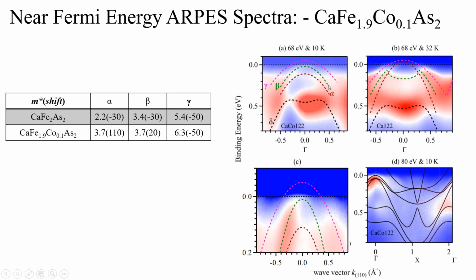cobalt doped compounds. So basically what I want to say is, with the cobalt doping, what do we expect? We expect that the Fermi energy will shift, the whole bands will go down. However, in this case, we see that the bands are not going down. Some of them are going down, but most of them are not. So it means that replacing iron with cobalt is not just leading to charge carrier doping. It is also creating a significant amount of correlation in the compound, which is not well captured in the DFT calculations.